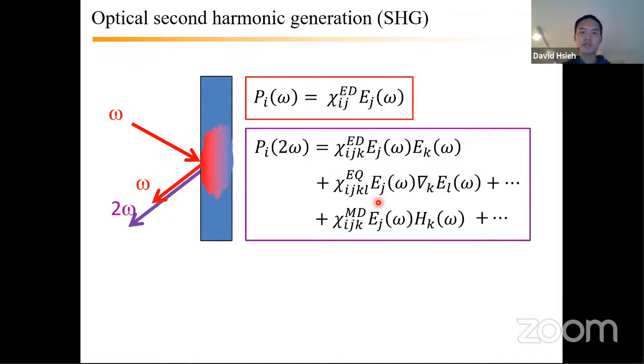Okay, so the particular nonlinear response we're looking at today, as I mentioned, is second harmonic generation. Basically that's the emission of light at twice the frequency of your incoming beam of light. So I already mentioned in linear response, when you measure omega in, omega out responses, you're primarily governed by this electric dipole second rank tensor. For SHG, you have to worry about a few more terms. Predominantly, you're dominated by this electric dipole response again, which includes two electric fields coming in, inducing a polarization in the material oscillating at twice the incident frequency, at 2 omega.